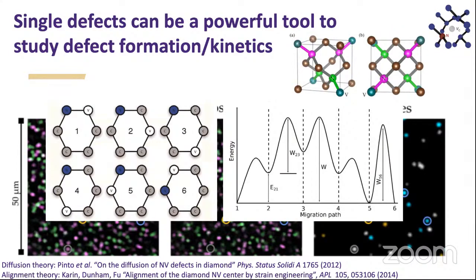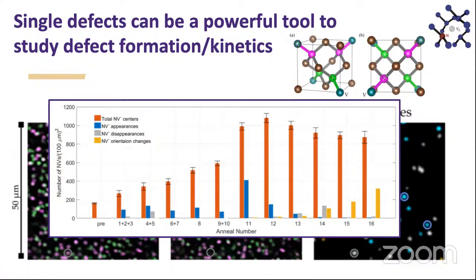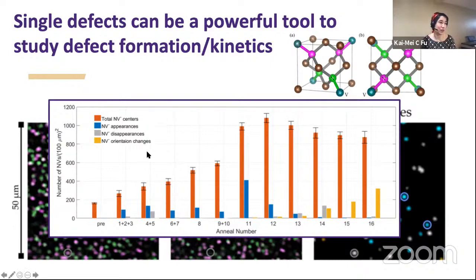The bar graph you showed previously didn't seem to have reached steady state to me. If you keep going, what happens? So we tried so hard to reach steady state. And if you look at this paper, you'll see that each of these last 3 anneals is 150 hours. Originally, we started with 2-hour anneals. And this was a massive undergraduate experiment where generations of undergraduates would anneal and map. And that was the only way it was possible, right? Because it's just so long.